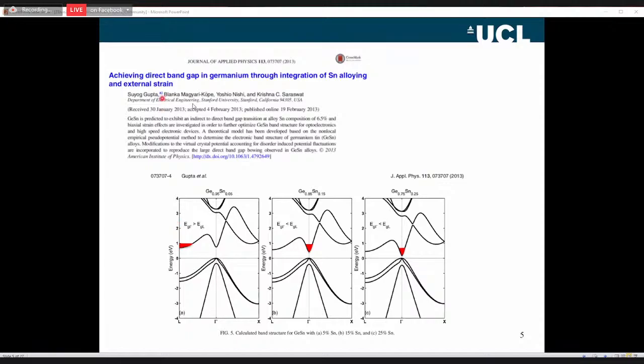The same group, I think different authors, but the same group, they've done some more detailed calculations using density functional theory. So this is a theoretical picture. This is 5% tin. You can see the L, I've just coloured in the lowest part of the conduction band. The L is the lowest part of the conduction band here. As we put more tin in, this is up to 15%, you can see this forms the lowest part of the conduction band. As we put a bit more tin in, it's still the lowest part of the conduction band, but we reduce the band gaps. We tune the band gap with tin. We can tune which is the lowest minimum. That's basically the theoretical aspect.